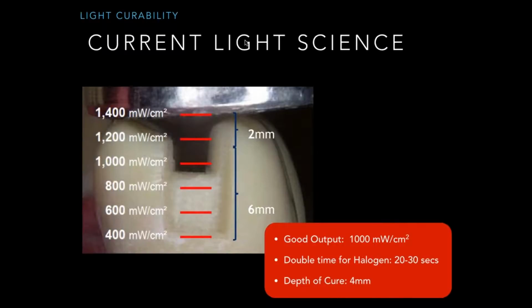The final component that influences adaptation is light curing. Clinicians should remember the following basic principles to ensure adequate light curing of composite materials. Deep composite resin restorations demand a high-quality curing light. You need to have good operator technique, and you need to make sure that the light is directly placed into the preparation as close as possible. You need to also provide sufficient curing time for every individual type or shade of material. Pay close attention to the depth of cure that manufacturers make. Most bulk filled composites on the market today claim a 4 millimeter depth of cure.